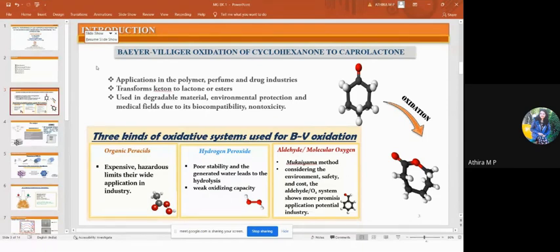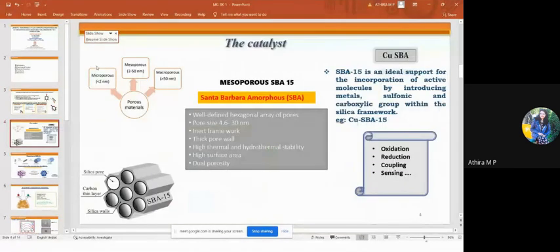Due to the speed up of initiation of the radical chain reaction, molecular oxygen prefers different metallic or supported metal or metal oxide as catalyst, which shows promising application in potential industry. Moving on to the catalytic part, use of support is identified as a handy tool to enhance the dispersion of catalytically active species, and supported metal oxide or mixed metal oxide and modified forms are suitable candidates to carry out the oxidation reaction with fairly good selectivity. Heterogeneous catalyst systems play an important role in organic synthesis as they can reduce the number of steps and minimize the use of expensive harmful chemicals. And here supported copper catalysts have been used for this reaction.